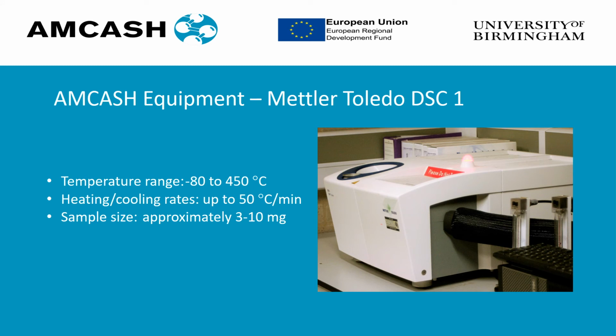In the AMCASH project, we have two different DSCs. The first is the Mettler-Toledo DSC1. This can perform over a temperature range of -80 degrees up to 450 degrees. It performs both heating and cooling cycles at a rate up to about 50 degrees per minute. The sample we use is typically between 3 and 10 milligrams.